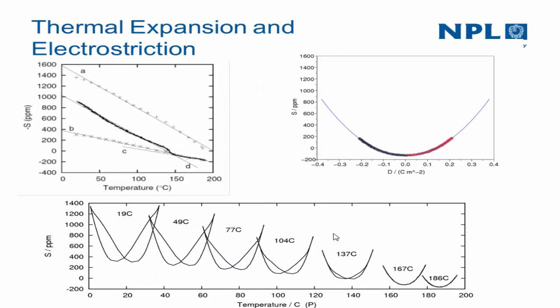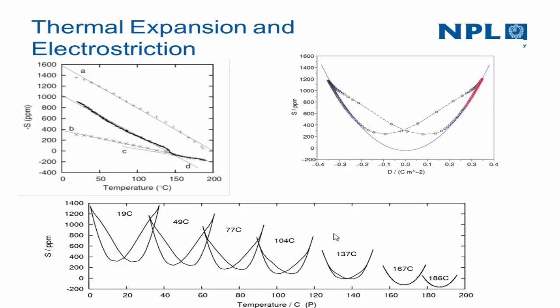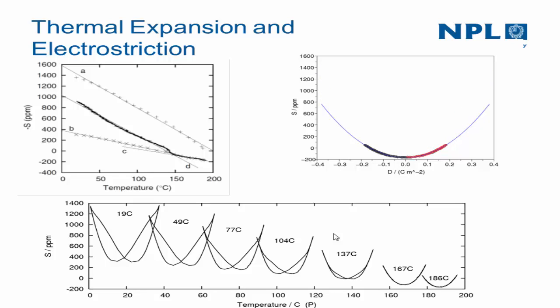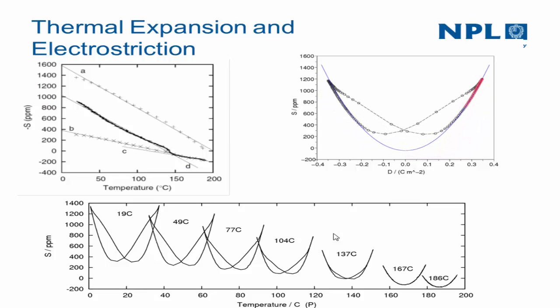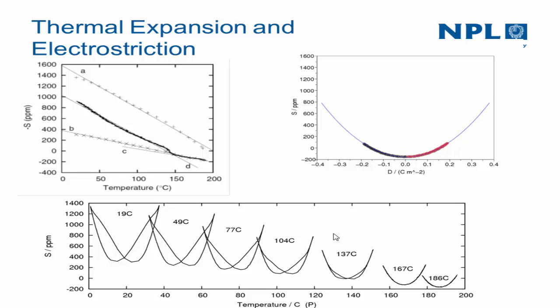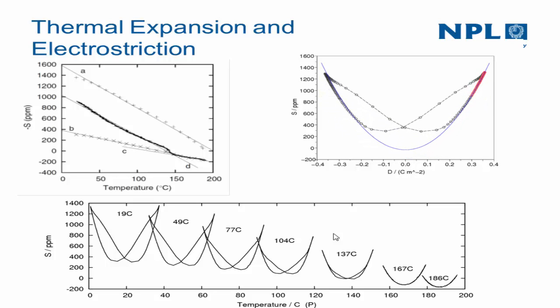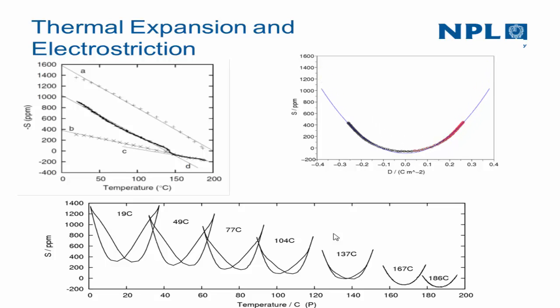Okay, and some of the work that we did on this low temperature material, the nice thing about a low Curie temperature material is that we can investigate these properties through the transition above the Curie temperature without all of the complexities of electrode materials and so on. And we can see with this that even the piezoelectric behaviour can still be described as an electrostriction. One way of looking at piezoelectric behaviour is that it's electrostriction offset by the remnant polarisation. And we were able to show that that really works quite well for parts of the loops over a wide range of temperatures.